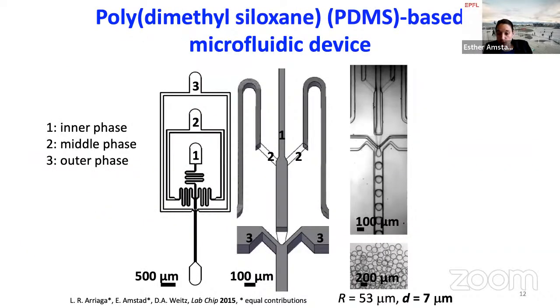Again, starting from what's well known in literature, and a lot of this work has been done while I was a postdoc in the lab of Dave Weitz, we still use double emulsion devices. Double emulsions are nothing else but small aqueous drops that are incorporated into a larger, in this case oil-based, drop that is dispersed in a third fluid. So you have water, oil, water systems. And this is a device that I introduced together with Laura in the group of Dave Weitz, and that allows you to produce these kinds of double emulsions with well-defined dimensions and relatively thin shells at reasonable throughput. So we could make about 1,000 drops per second.